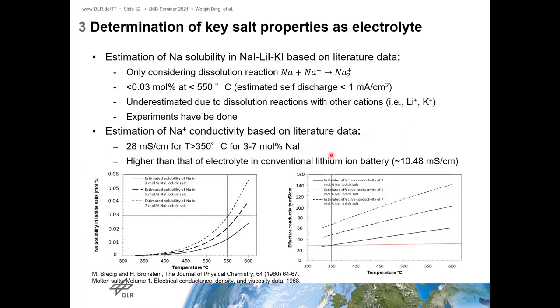And then we do the determination of the key salt properties as electrolytes, for example, the sodium solubilities and also the conductivities. For the solubility from the simulation, we already consider the dissolution reaction. According to the literature, we find that below 550 degrees C, its solubility is quite low, and the estimated self-discharge rate is also low enough. But the value can be underestimated, maybe due to other dissolution reactions. The experiment has been done. I will show you later.